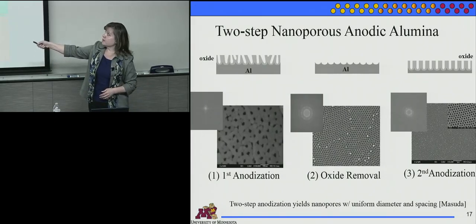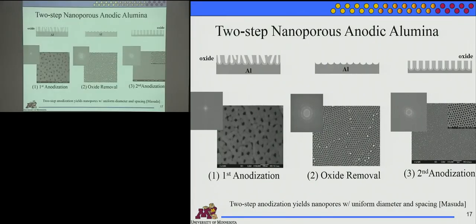But the further you grow this oxide, the ordering is actually happening at the aluminum oxide-aluminum interface. And as that interface is ordering, it means that the longer you grow that oxide, the more ordered these dimples basically become in the aluminum. When you etch that oxide away, then you have aluminum that actually looks like this. So that's the metal now.